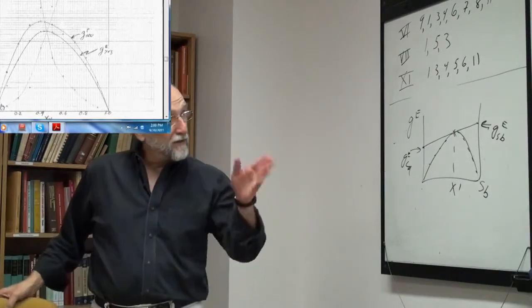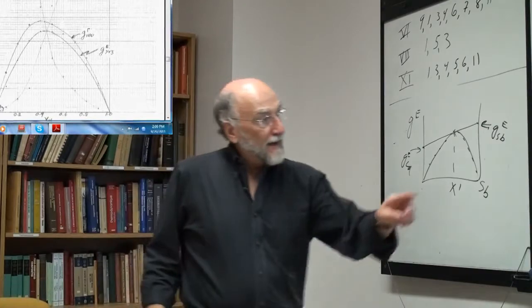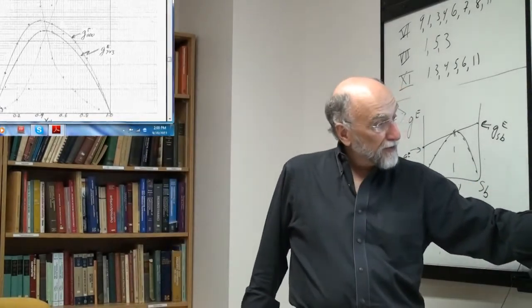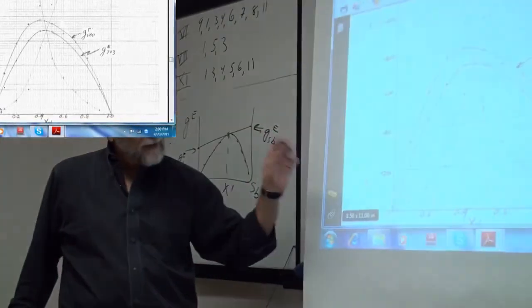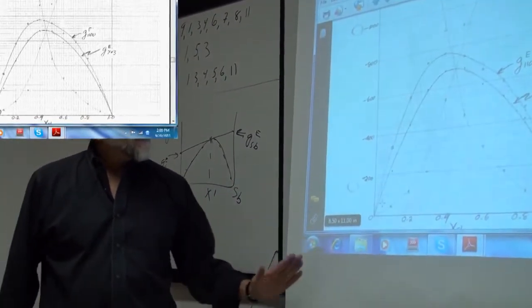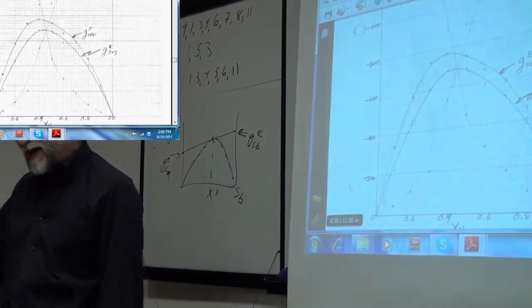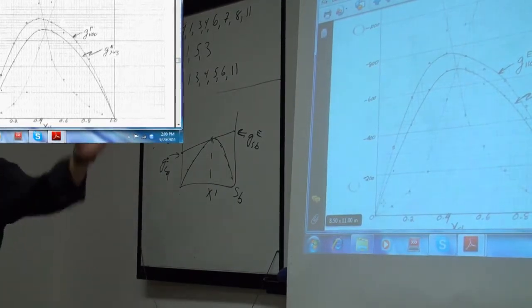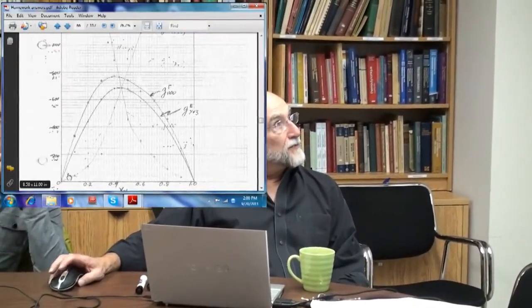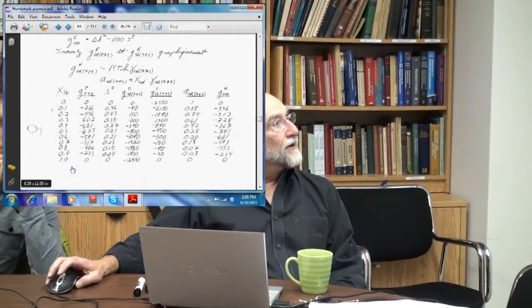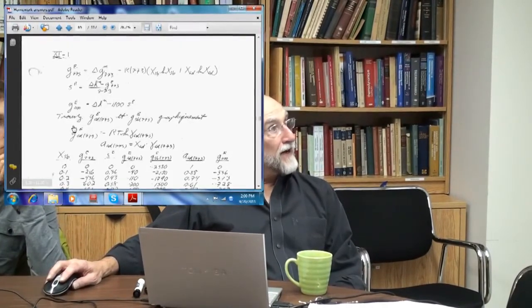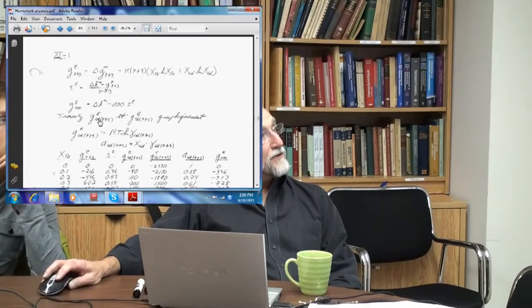As I'm adding antimony to cadmium, the ideal entropy term at the limit is minus infinity because there's an infinite number of ways of putting it in. The excess term is due to the fact that the antimony-cadmium bonds have a different energy than an antimony-antimony bond. That gives you the excess partial property, which is obviously not infinity, it's just the difference. So that gives you the excess partial GXS. I find the excess partial properties graphically.